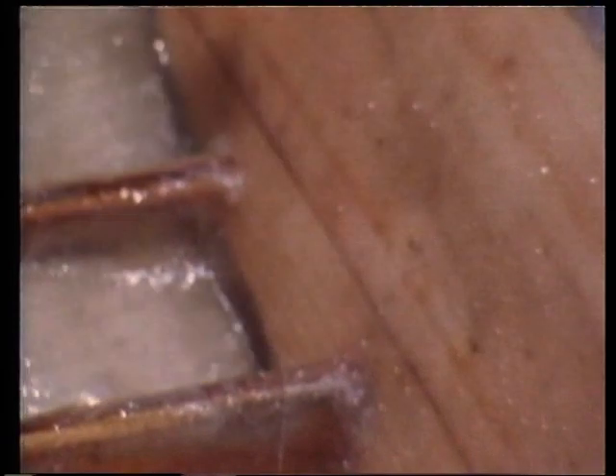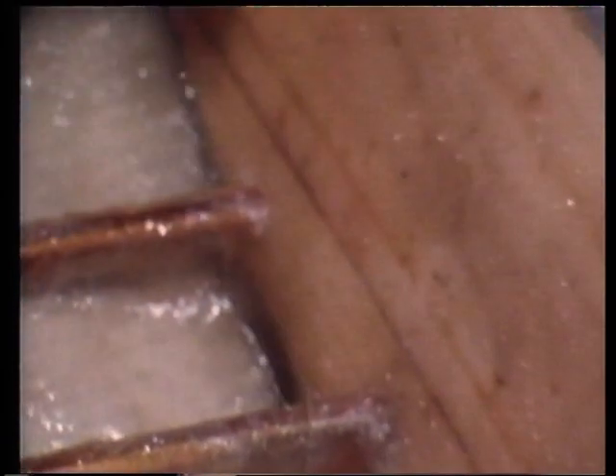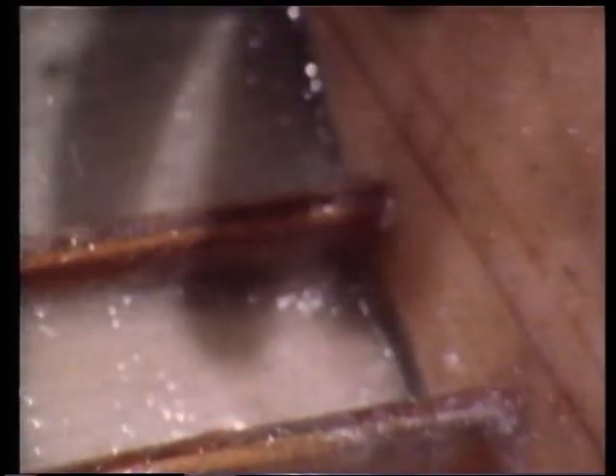There are stresses set up during the curing process. The exotherm, the heat generated by the laminate as it cures, must be allowed to dissipate completely, the laminate cool right back down to normal room temperature, and sit there for quite a few hours before you attempt to release it. So we'll come back and release it as soon as that happens.